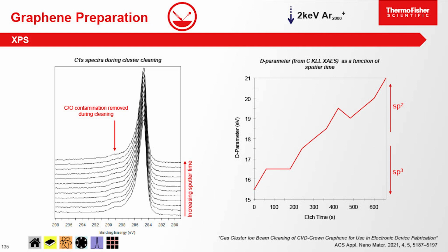This is indicative of the contamination at the surface, and then as we clean it, we get towards 21, 22 eV value, which is what we would expect for graphene. So we're cleaning it, and from this measure, we can see that we're getting to graphene. However, we don't know from XPS whether the surface is actually staying stable or not, whether we're damaging it, because we're firing ions, even cluster ions, at the surface. Is that damaging the graphene material?